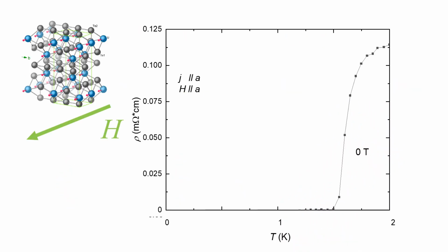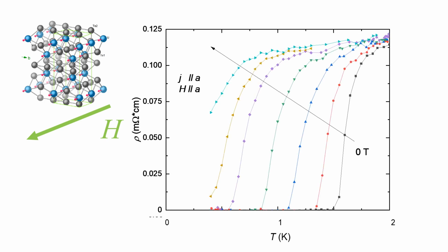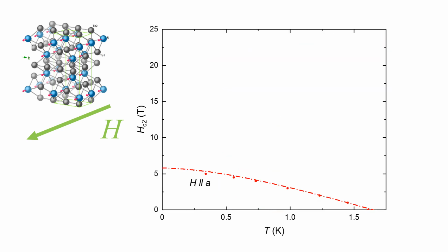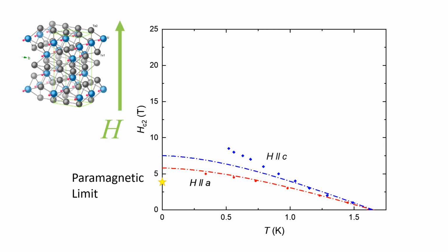Now let's see what happens when we apply the magnetic field to uranium ditelluride. Uranium ditelluride is an orthorhombic system, so the three axes are all different. We first apply the magnetic field along the a axis. Indeed, superconductivity is quickly suppressed by the magnetic field. Here, I plot the critical field as a function of temperature. It follows a theoretical model for the orbital limit pretty well. And here is the paramagnetic limit. When we apply the magnetic field along the c axis, it starts to deviate, but only a little bit.